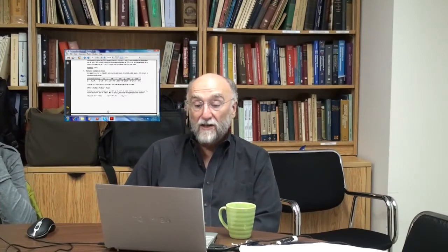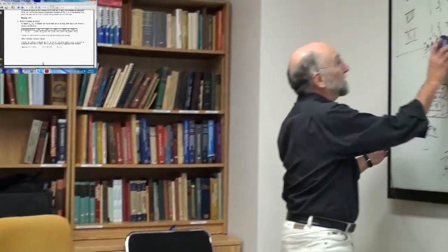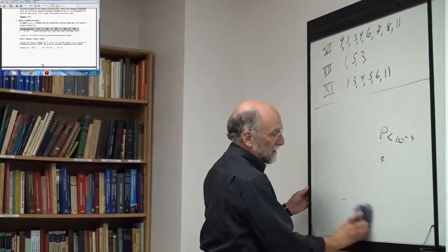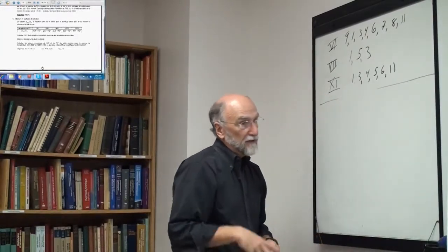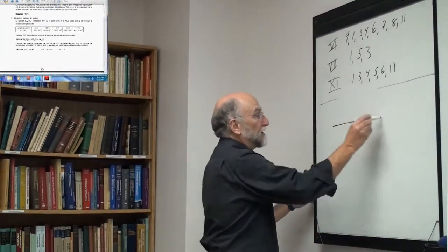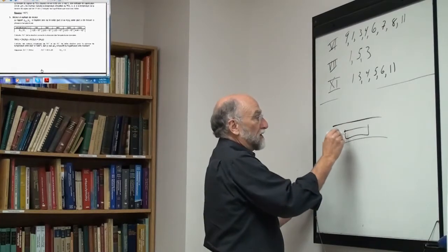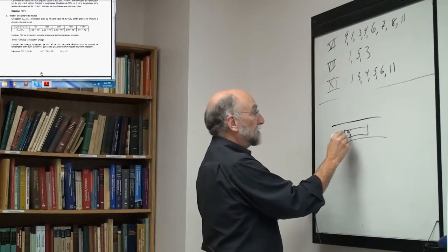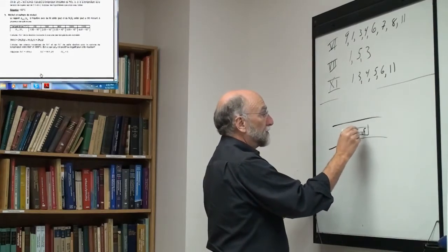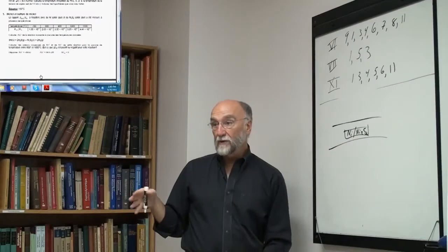Number 5. Nickel and nickel sulfide. Okay, the ratio of pH2S to pH2 at equilibrium with solid nickel and solid nickel sulfide has been measured at several temperatures. So this is again the classic gas equilibration technique. I showed that in question 6.1 for the iron carbon thing. It's the same thing. Now you have a boat here containing nickel and Ni3S2, a mixture of the two powders.